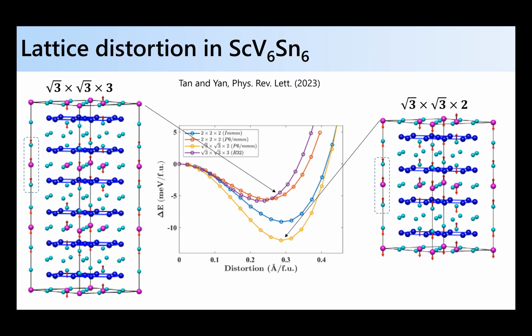Okay, so what's going on with the charge order in this system? If you look at the DFT-predicted instabilities of this lattice, this is some work by Binghai Yan's group. DFT predicts that the most energetically favored distortion is not the experimentally realized root 3 by root 3 by 3, but instead this root 3 by root 3 by 2. So the same type of in-plane periodicity, but a shorter modulation along the c-axis. And the question is, why the discrepancy? And is the discrepancy interesting? I'll try and motivate that I think it is interesting.